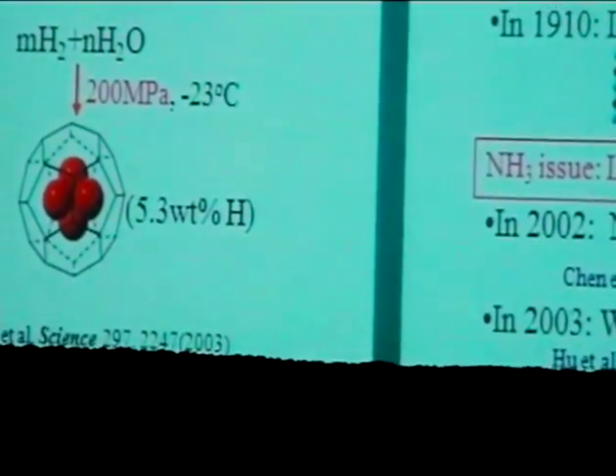The reason is because of water: at high pressure and low temperature, it can form a cage and capture hydrogen inside the cage. So you can see we need 200 megapascal and minus 23 degrees C. Then you can form this hydrogen water cage with the hydrogen captured inside. So the theoretical capacity can reach 5.3%. That's theoretical, and that paper was published in Science in 2003.